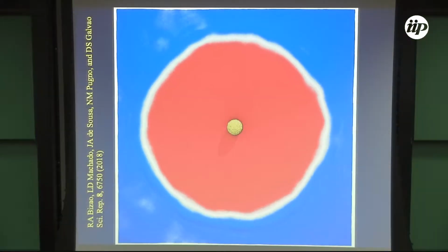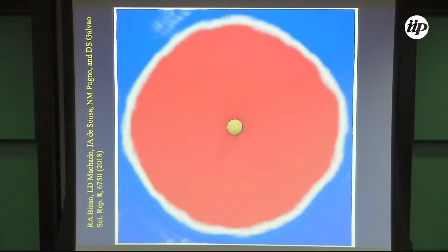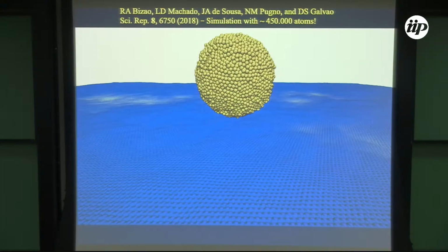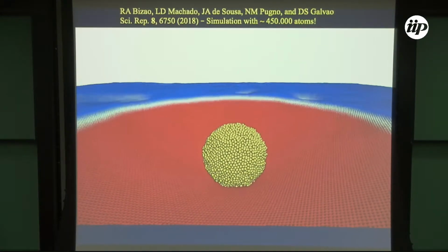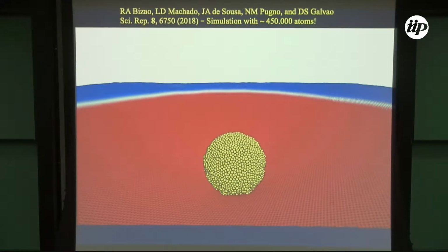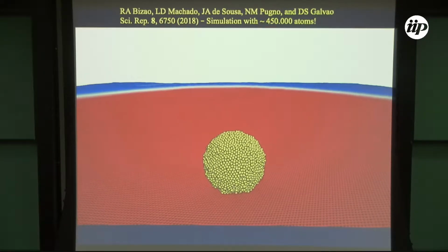And we now have the tools to simulate this material. This is a simulation of about 450,000 atoms. We try to mimic the experimental conditions. We should see the elastic wave propagating. At first you still have the hexagonal topology, but as the elastic wave propagates, it becomes more like a spherical one. And if you shoot with enough kinetic energy, you break the structure. See again the elastic wave propagation, and now it starts to break.